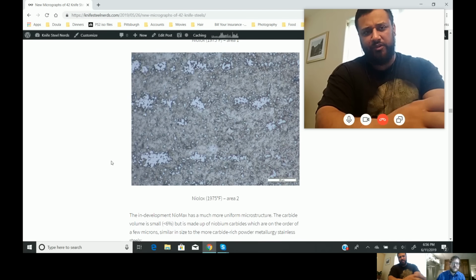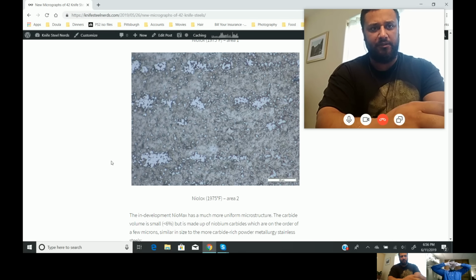Which is interesting. This stuff doesn't have a mind-blowing amount of vanadium or niobium, right? I think it was like 0.90 vanadium and 0.70 niobium for this material. It's less than 1% for both of those. Yeah, but we get these big old honkers. Yeah, most of those bigger carbides are from chromium. So maybe if they could control the carbon and/or chromium content a little better, they could get rid of them. But they don't seem to be looking into that right now.